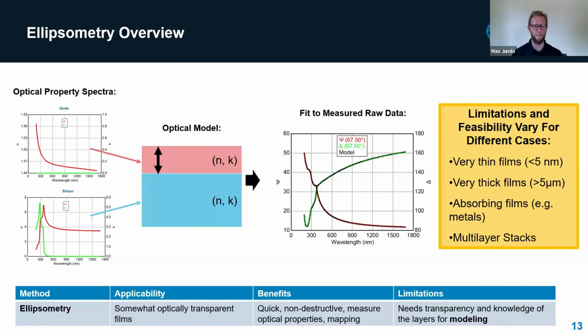We get these two lines that tell us how the polarization state changed, but that's not film thickness, which is what we're interested in. So how do we get to the film thickness? And to do that, we have to fit an optical model to the raw data that we collected. And so I'm showing a schematic of a really basic optical model in the middle here. And there's really two main components that go into optical models. You have the optical properties, which are N and K. That's the index of refraction and the extinction coefficient. And those are material specific. They're basically like a fingerprint that describe how that material affects light, how fast the light travels in it, and how much that material absorbs the light.